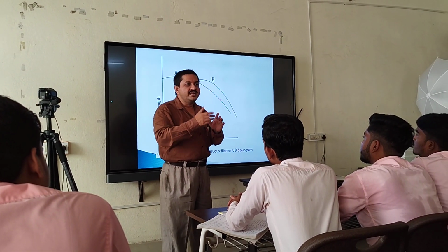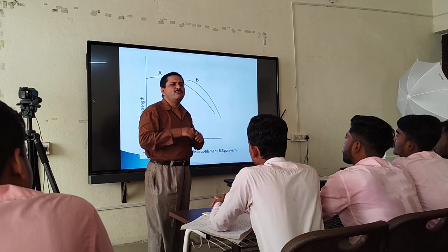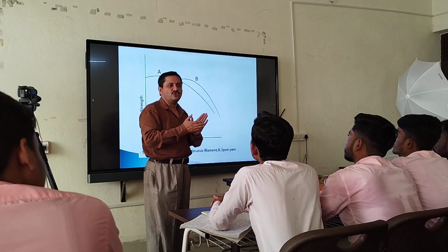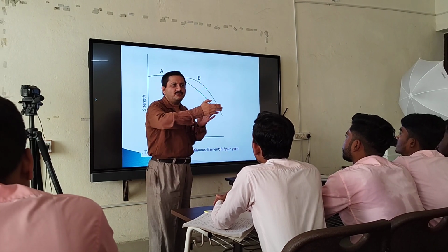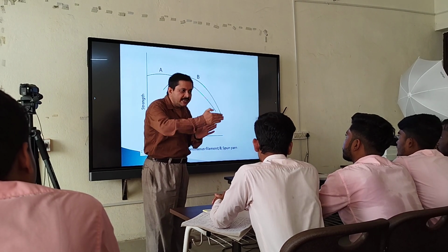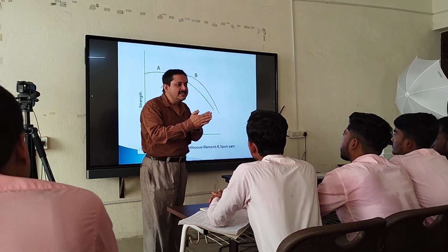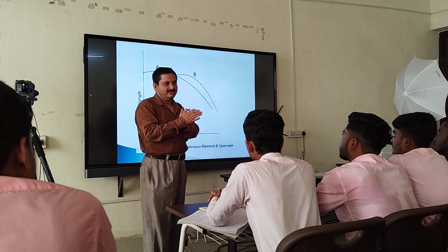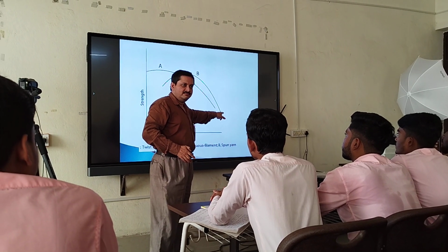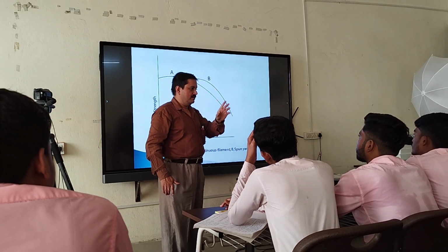Surface fiber breakage after the optimum level. If surface fibers break, what will happen? The compressive force will decrease, yes or no? Breakage or rupture of surface fibers causes a decrease of compressive force, which means a decrease of fiber to fiber friction, and ultimately you observe the declining nature. That's why we always try to keep up to the optimum. Clear?